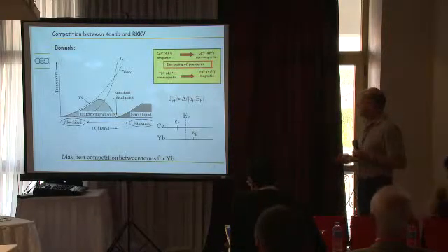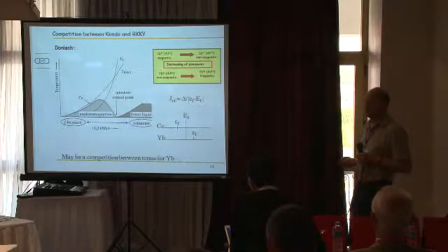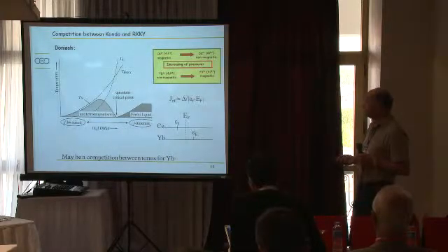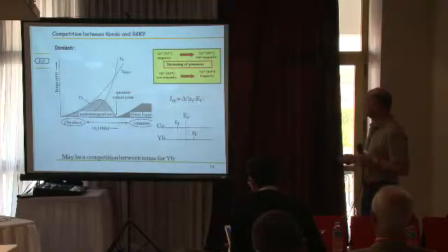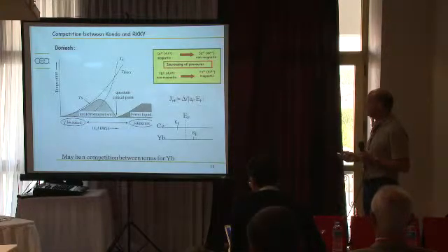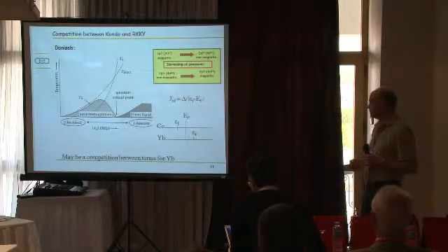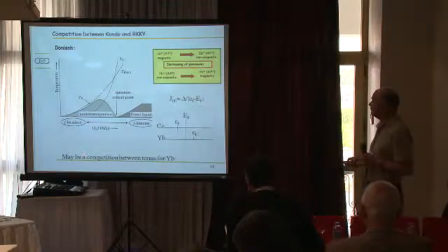Now you see, for cerium, the relation between pressure and J is obvious, because delta, the width of the level, will also increase with pressure. So this term increases, this one decreases, and J will increase with pressure. In ytterbium, delta will probably also increase, so you see there might be a competition between the two terms. So we can normally expect that J will decrease with pressure.